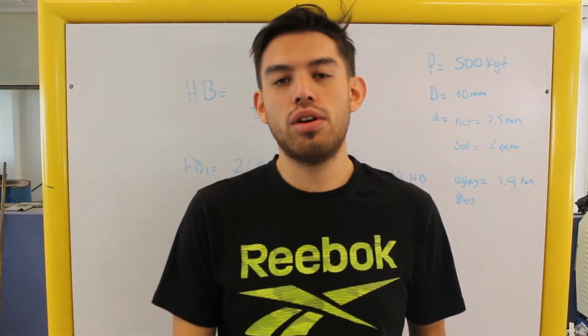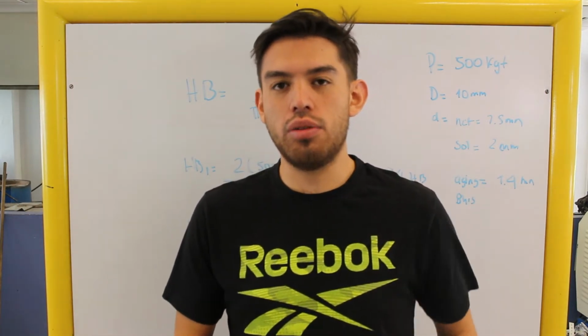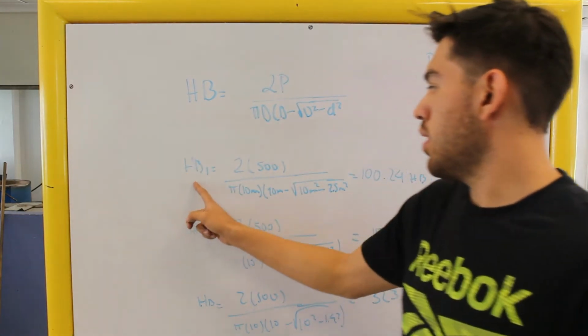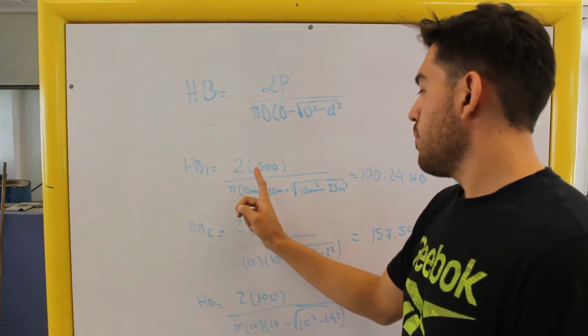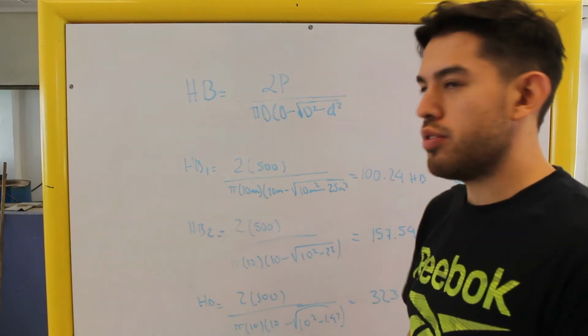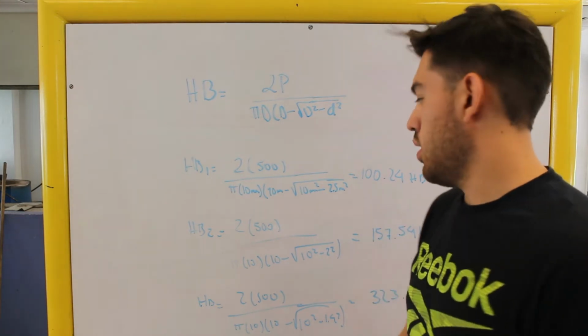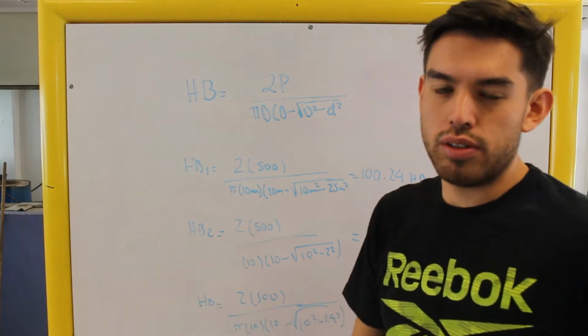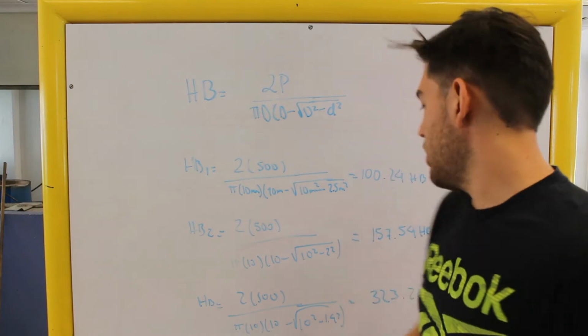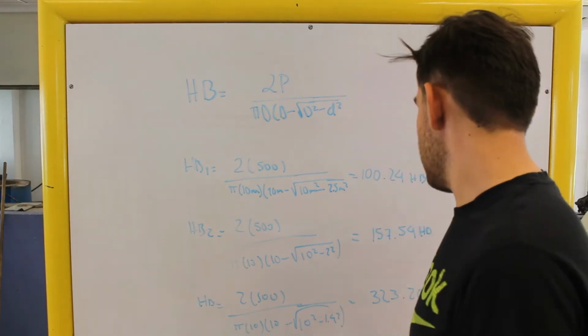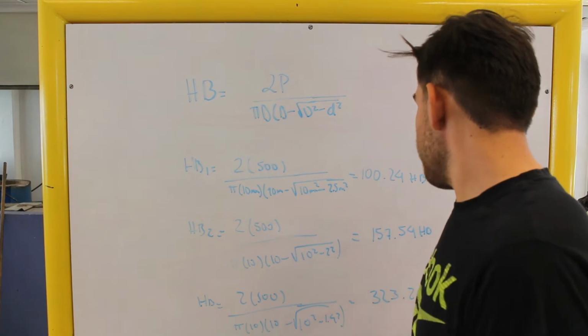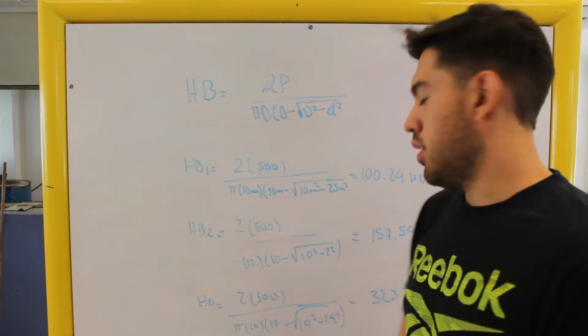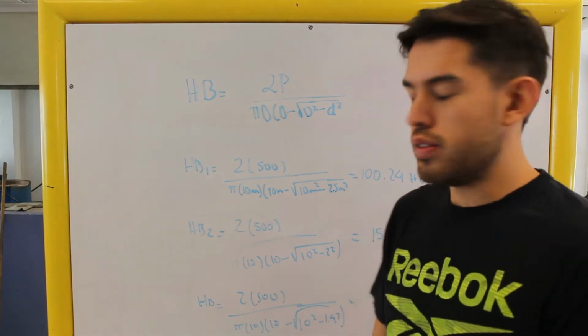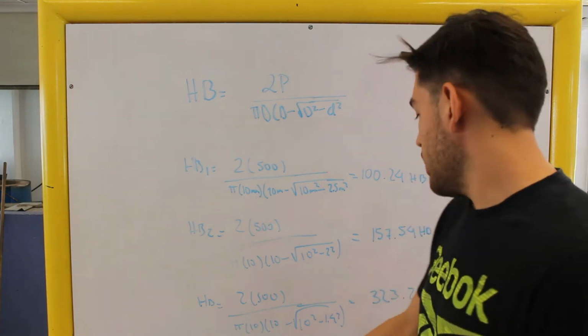We made Brinell hardness tests in our different materials: with no heat treatment, with solubilization, and with the aging at 8 hours. And we got these numbers. For the first, with no heat treatment, with this formula we got 100.24 hardness. In the second one, with the solubilization treatment at 530, we got 157.54 hardness.